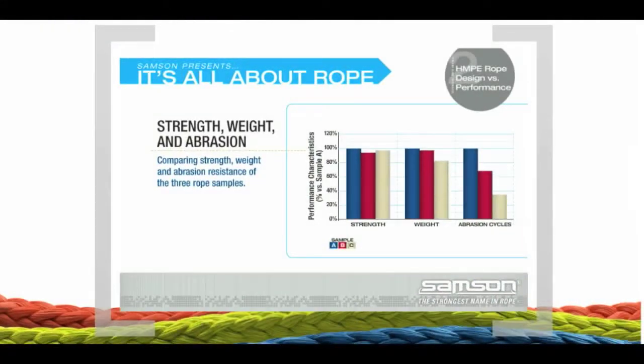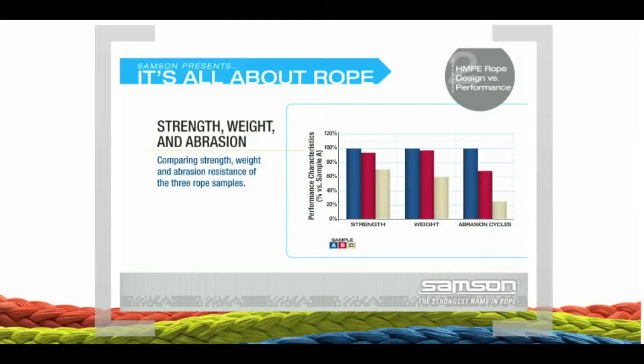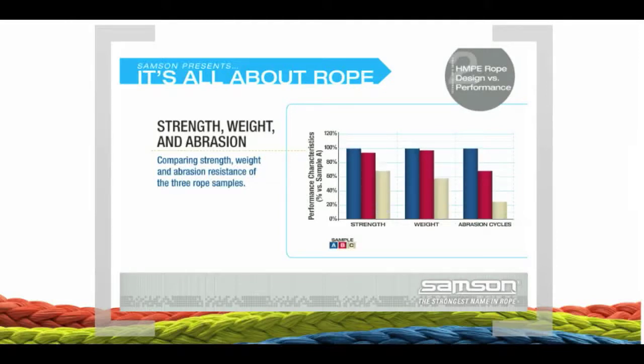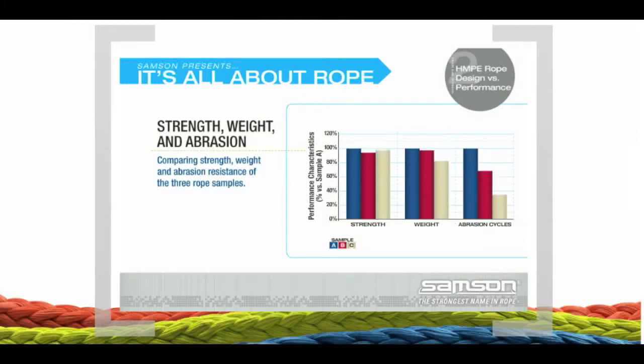This chart compares the strength, weight, and abrasion resistance of the three rope samples. The looser, longer cycle length rope is slightly stronger and weighs less than the other two samples, but it is significantly more prone to abrasion damage than the other two. Field observations of ropes in use confirm that the result of longer cycle lengths is increased snagging and surface wear. Since surface wear is the leading factor in strength decay of HMPE rope, service life is clearly compromised.